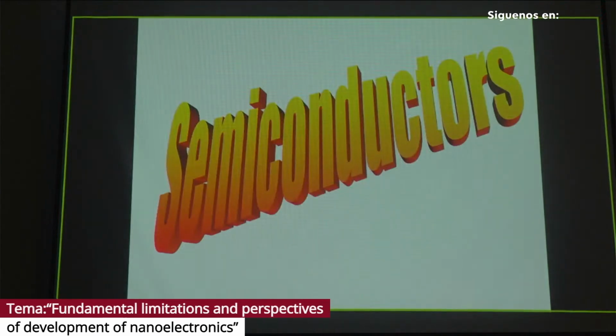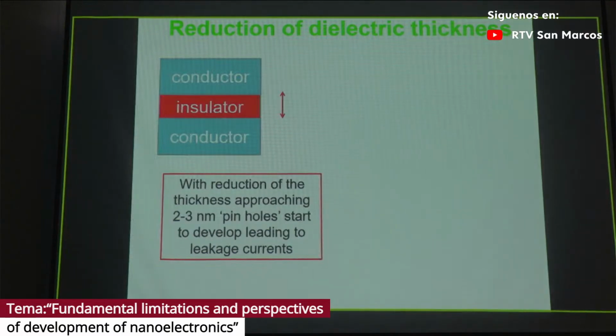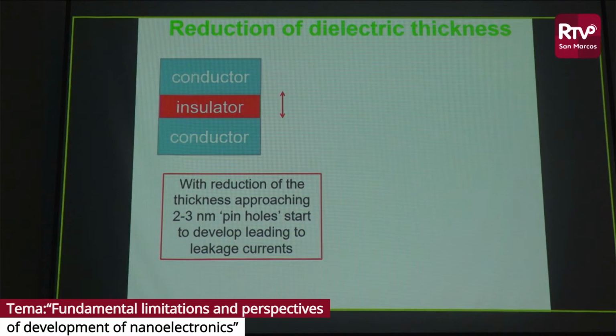So now what about the other typical material used in microfabrication all over the world, semiconductors? First of all, let us suppose that we have a very simple device used in all electronics, let's say a capacitor, which consists of 2 plates of metal separated by an insulation layer. If we want to downscale our object, we should reduce everything, including the red insulating layer. But nature doesn't like this. As soon as the thickness of the insulator becomes comparable to a few nanometers, pinholes start to appear. So such a capacitor with reduced dimensions will not work anymore as a capacitor.